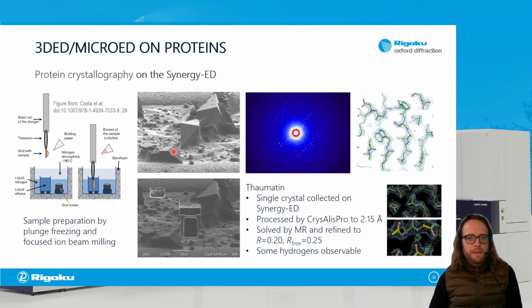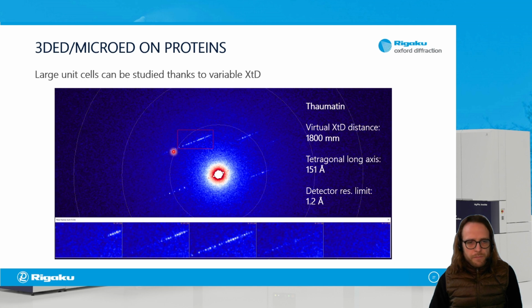So if we just kept the detector distance at what you would use for small molecules, the peaks would just be too close together to still integrate them. But what you see here is, again, the same data set. And for this long axis of the tetragonal unit cell, we could still nicely resolve the peaks here by tweaking up this virtual detector distance to 1.8 meters. And thanks to that, we could solve the structure and integrate those intensities nicely. And along this long axis of our anisotropic detector, the resolution limit is still quite a respectable 1.2 angstrom. So even for proteins, you can measure to such a high resolution if you're lucky enough to have crystals that diffract to such a high resolution, of course.